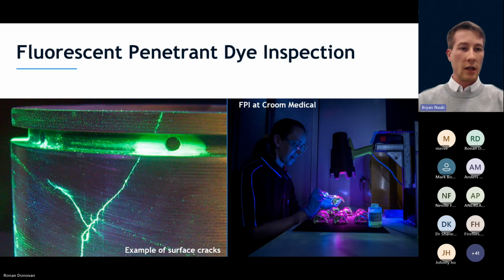And then I'd be remiss if I didn't touch upon a more conventional technique for inspecting parts and identifying defects. This is actually a process we offer here at Croom as well for our customers. So this is a fluorescent penetrant dye inspection. Essentially, the dye is applied to a surface and it will highlight any surface cracks or surface defects from AM processes or casting processes, forging processes, and so on. And this is a conventional method of inspecting your parts. Since micro CT scanning can be quite time consuming, this is often a better solution for high volume production, although it doesn't really tell us anything about the internal defects in the parts.